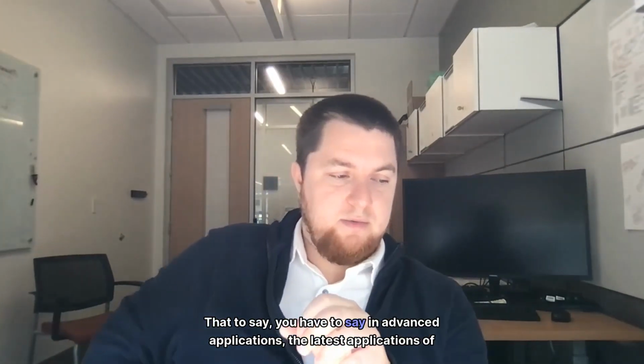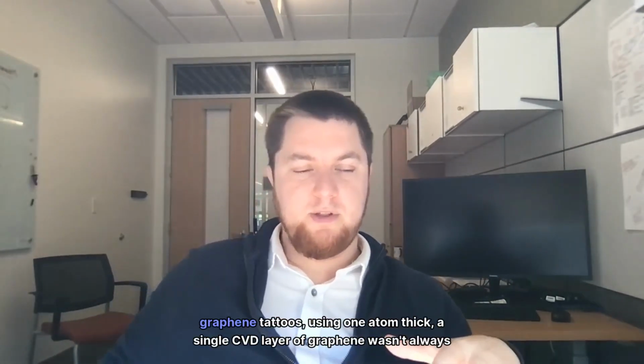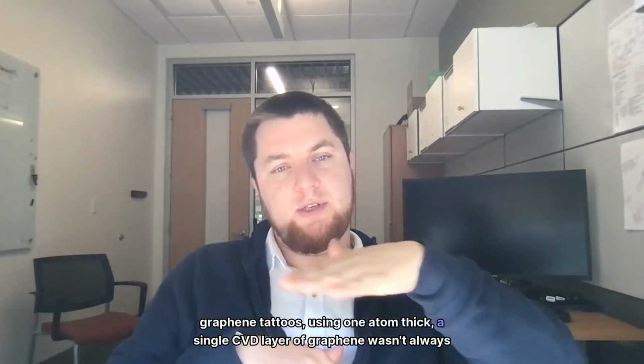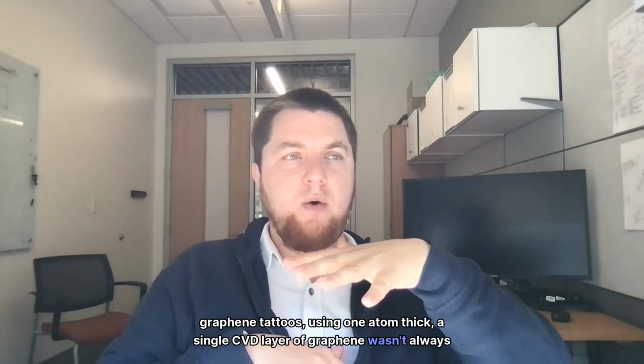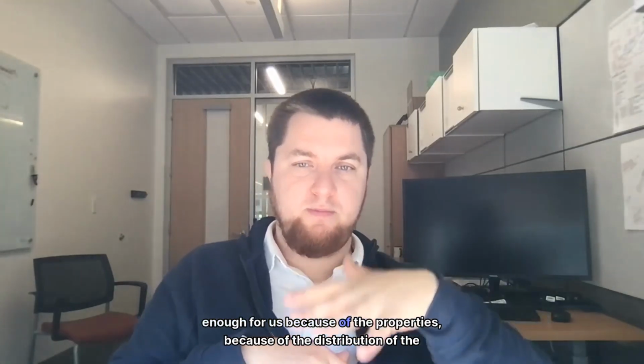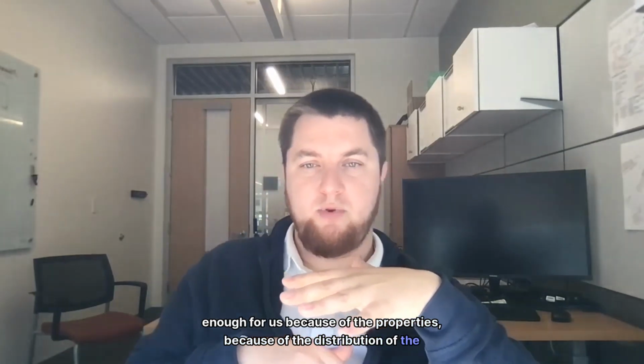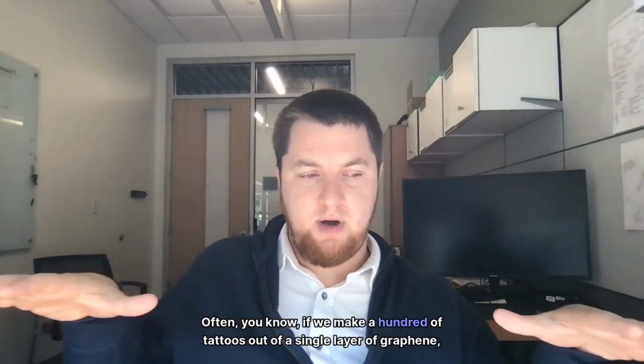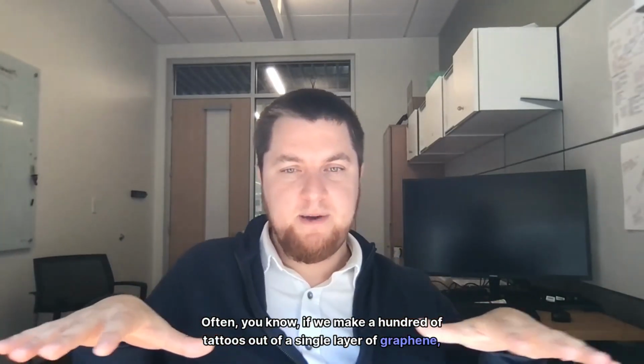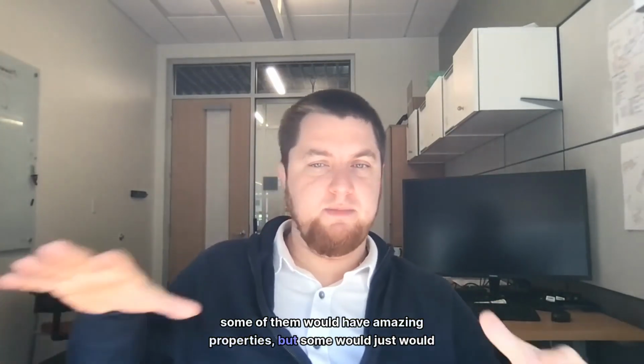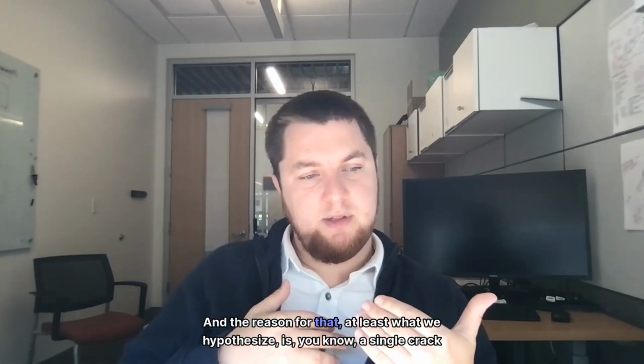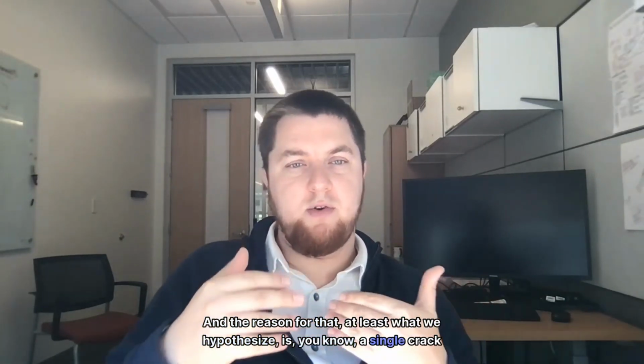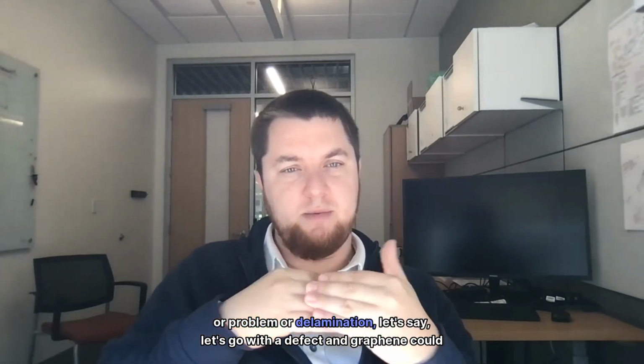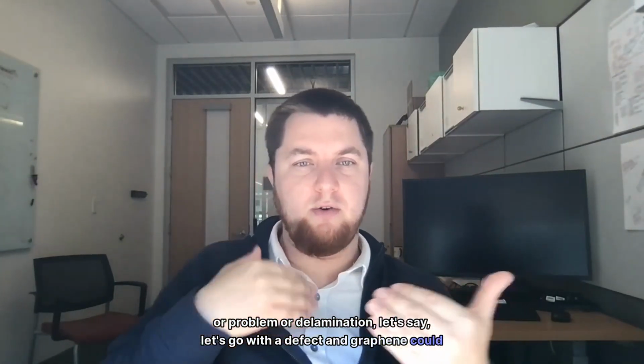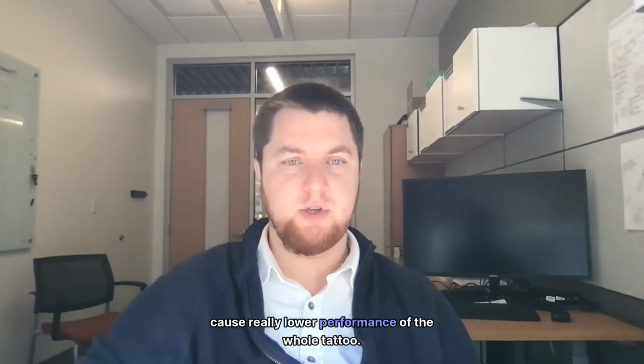That said, in advanced and latest applications of graphene tattoos, using one atom thick, a single CVD layer of graphene wasn't always enough for us because of the distribution of the properties. Often, if we make 100 tattoos out of a single layer graphene, some of them would have amazing properties, but some would be orders of magnitude lower. And the reason for that, at least what we hypothesize, is that a single crack, or delamination, or let's go with a defect in graphene, could cause really lower performance of the whole tattoo.